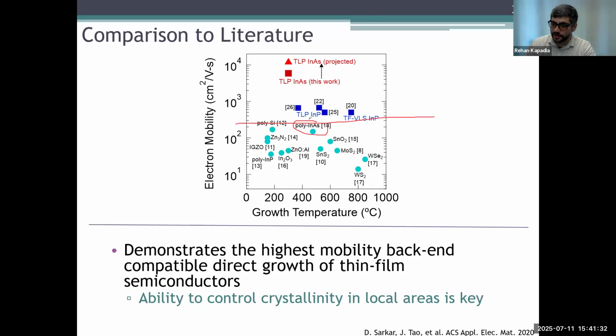Here's what vapor phase polycrystalline indium arsenide gives you, something like 200 centimeters squared per volt second, and this is what we're experimentally observing, which is on the order of 6,000 or so. So we're getting almost a 10x increase in quality compared to any other approach for any other material here. But if you look at a single crystal epitaxial material, it's still up here. So we're much higher than any other approach, but there's still a ways to go if we want to make the highest quality materials possible on these non-epitaxial substrates. And so there's still stuff that we don't understand. That's the takeaway there.